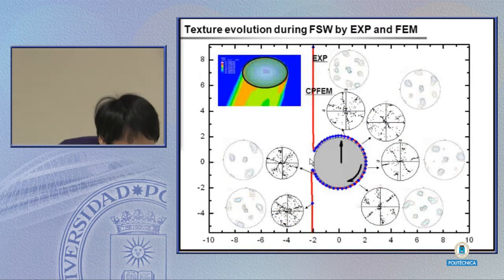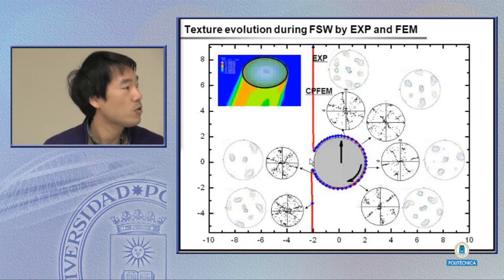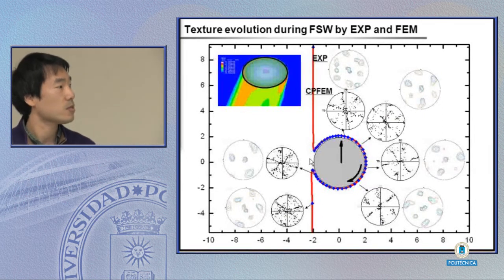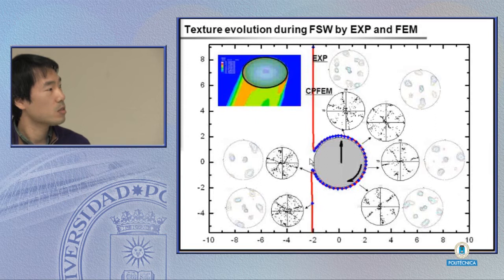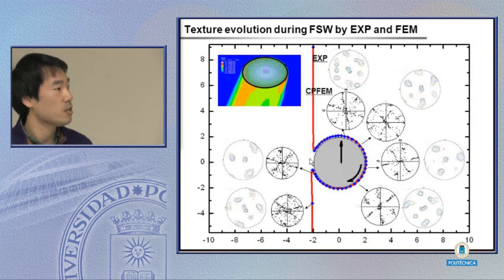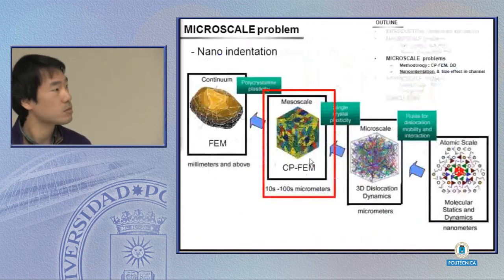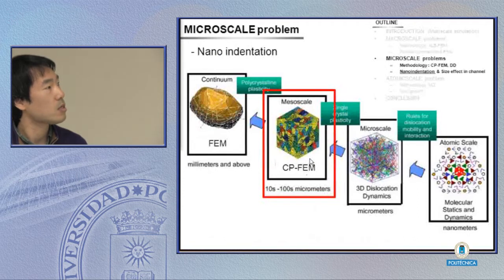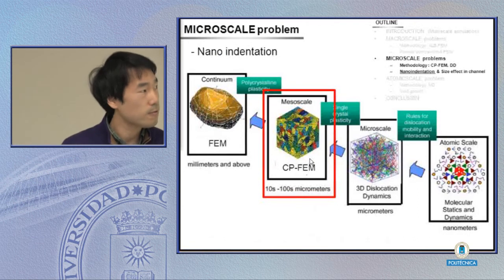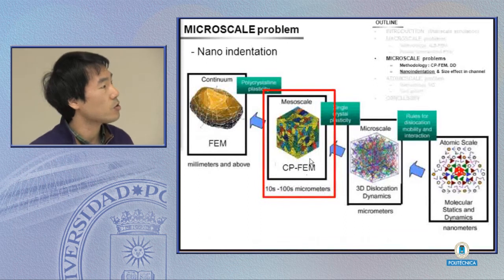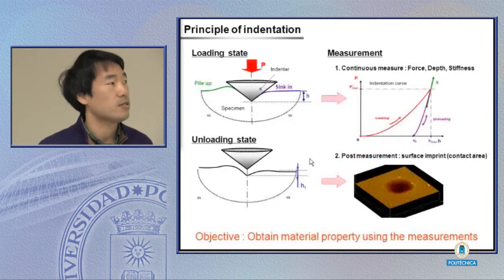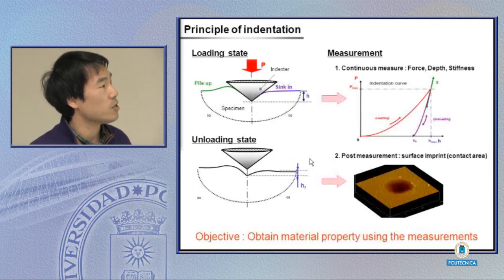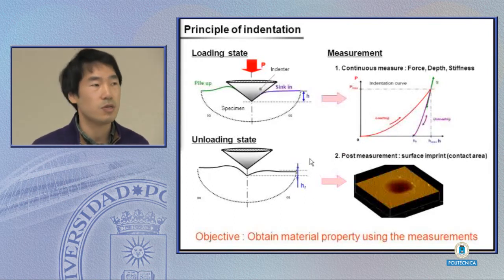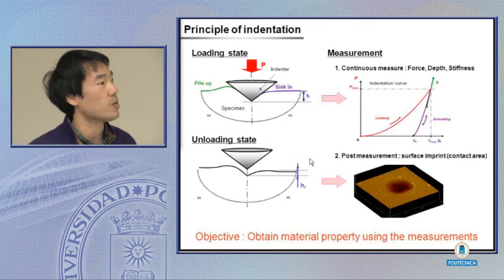And we can see the temperature heat flow during the FSW simulation, FSW experiment. So you see the heating is due to the friction, and then it flows like this. Also, we can follow the material flow during the FSW, and we also simulate the texture evolution, and it is confirmed by the experiment.